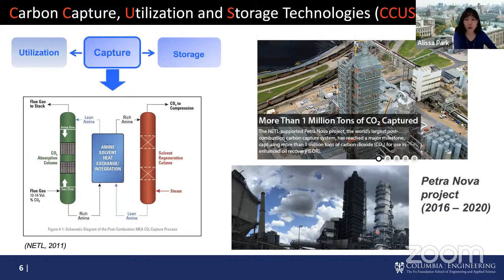They were capturing more than 1 million tons of CO2, and they stopped in 2020, but they will be resuming their operations soon. The particular material they targeted is the most studied one: liquid amine solvents, an aqueous, water-based liquid solvent system. And it's a chemical reaction. So you're doing catch and release by reacting the amine with CO2, making carbamate.